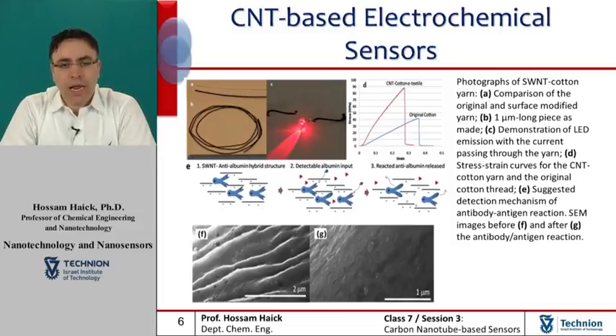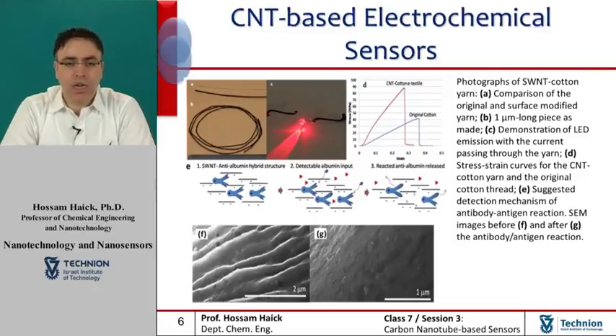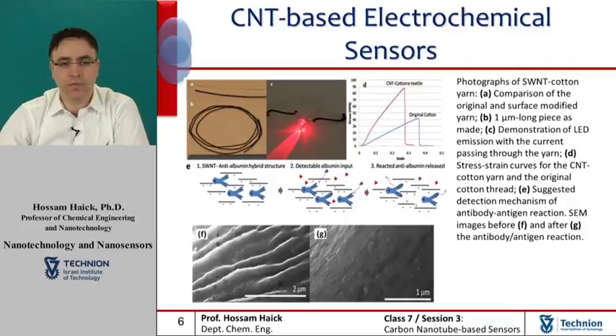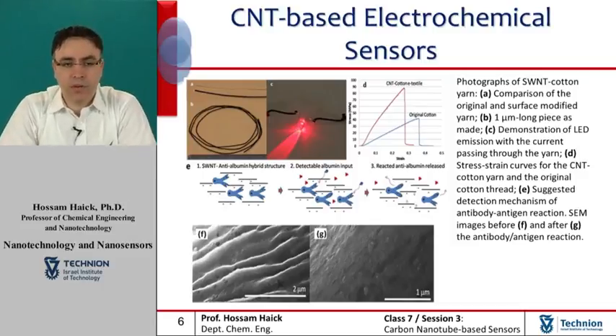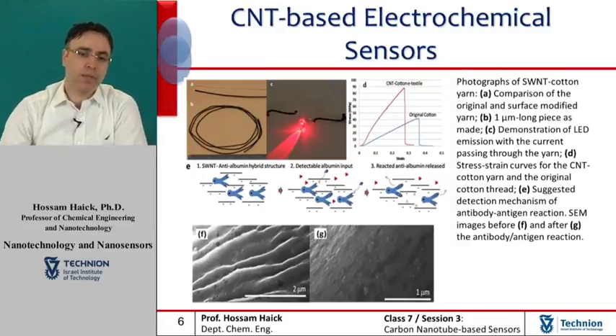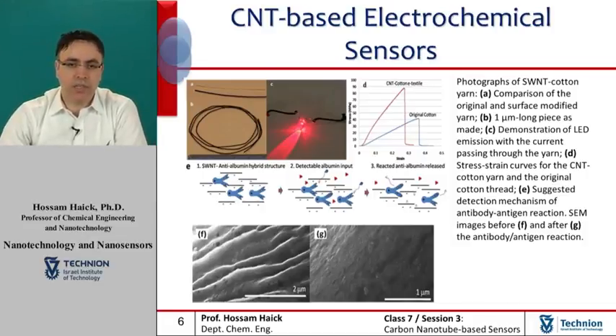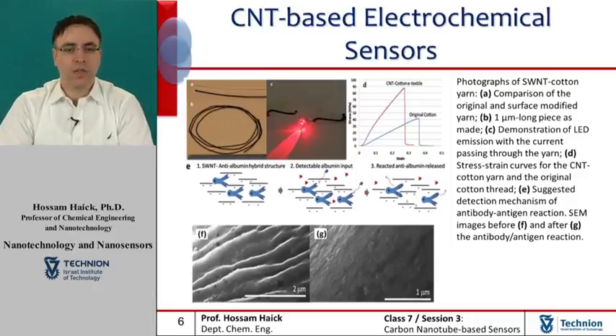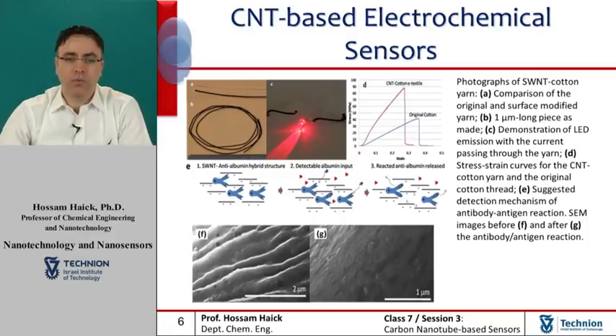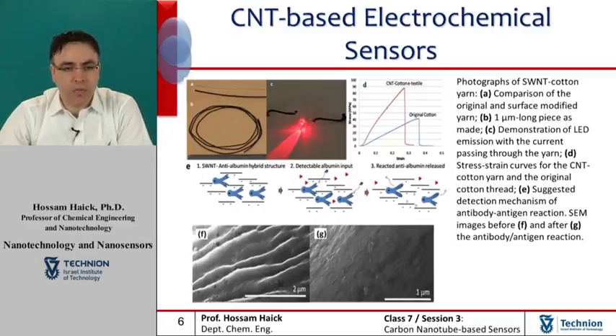In this method, cotton has been coated with carbon nanotubes and polyelectrolytes. The resulting carbon nanotube cotton cloth shows high electrical conductivities as well as some functionality due to biological modification of the intertube tunneling junctions. When the carbon nanotube cotton cloth incorporates anti-albumin, it becomes an electronic textile biosensor that qualitatively and selectively detects albumin. Single-walled and multi-walled carbon nanotubes are dispersed in dilute Nafion ethanol or PSS water solution. A general commodity cotton thread is dipped in the prepared carbon nanotube dispersions and dried, as seen in figures A and B on the screen.